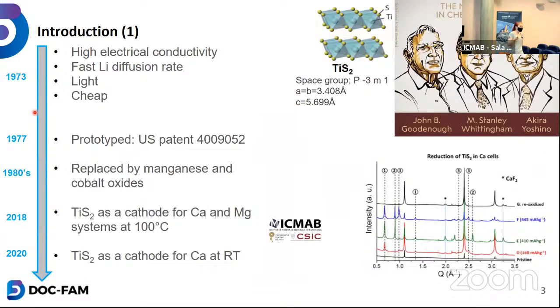We use propylene carbonate because the solvent used in that study of calcium was the electrolyte, calcium BF4 in PC. So this is why in the lithium system we wanted to use the same solvents. We also wanted to try different solvents to see which one was triggering the co-intercalation. But originally we really wanted to have something very similar to the calcium system. And then we added more solvent and more salt to test and to understand a bit better.